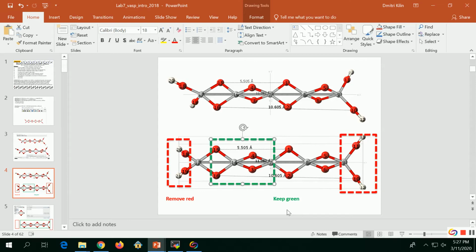If I do not take special measures, it will put the next oxygens right here on the same y coordinate as titanium, and it will substantially shrink the bonds between this titanium and the next, and the oxygens in the subsequent elements. So in addition to the elements in the box, I will need to account for this empty space, for a vacuum between periodic cells.